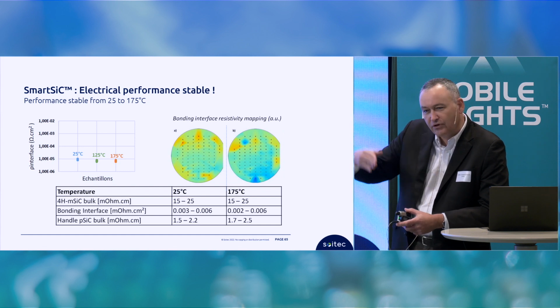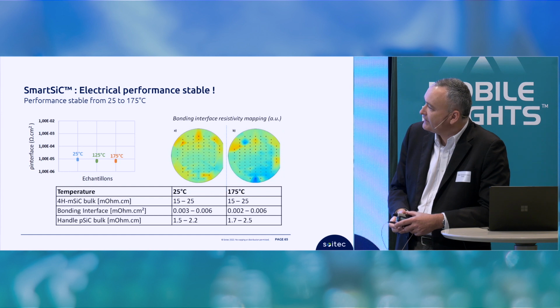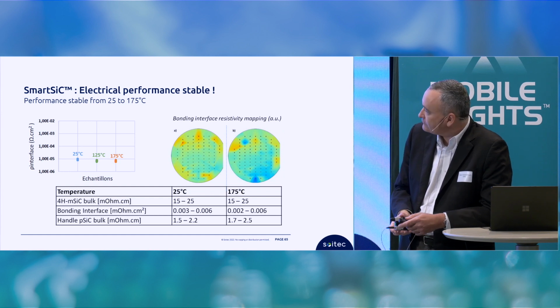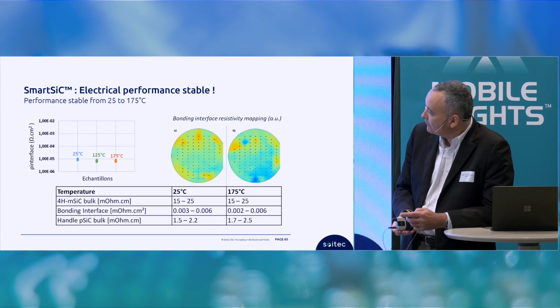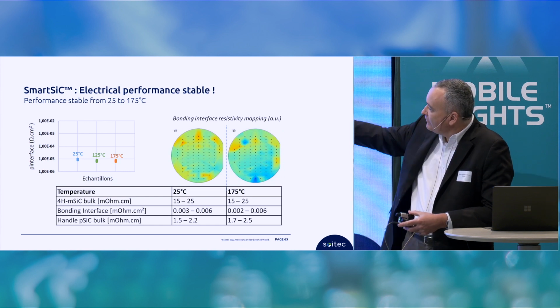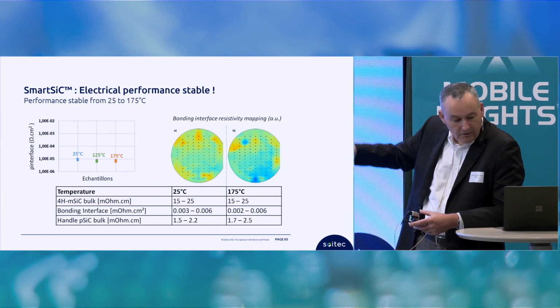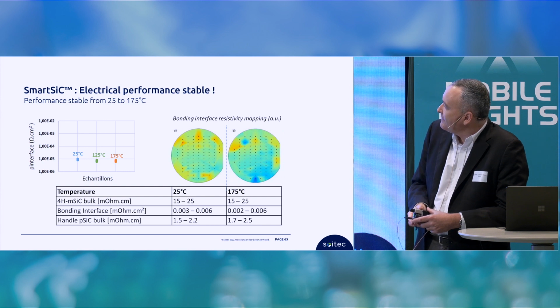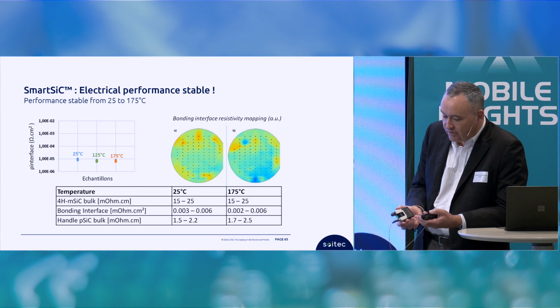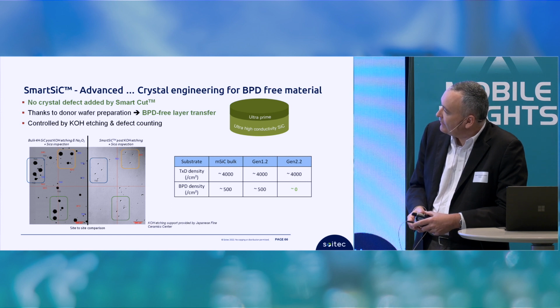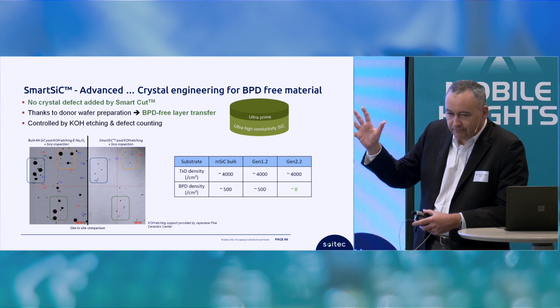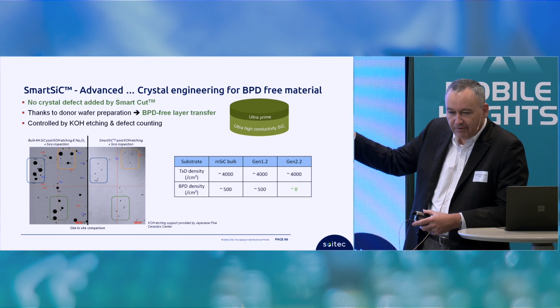Okay, now it's nice, but also the device operating temperatures. Typical power devices operate at 175 degrees. And so we have, in both cases, a very low electrical resistivity for the substrates, and so at the end, a significant improvement on the dissipation of the power device. Again, okay, it's good for SmartSiC performance product.